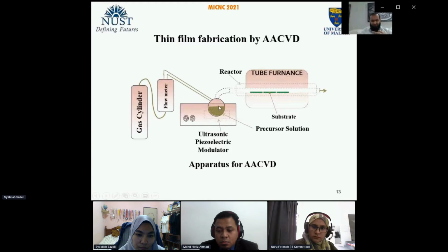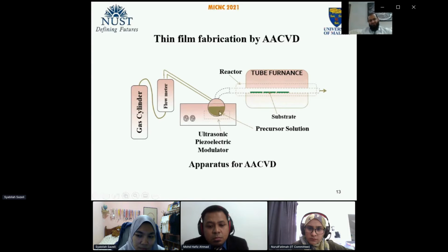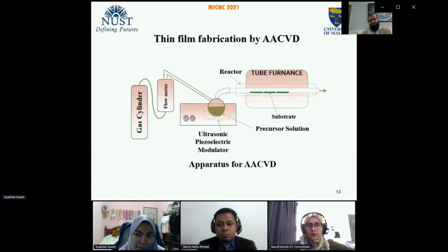Once it is soluble in organic solvent, we place the flask on the ultrasonic piezo-modulator. It agitates the solution containing our targeted precursor. Like in the present study, we have to prepare chromium oxide and manganese oxide. The precursors are chromium acetate and manganese acetate. So chromium acetate and manganese acetate are dissolved here and agitated.